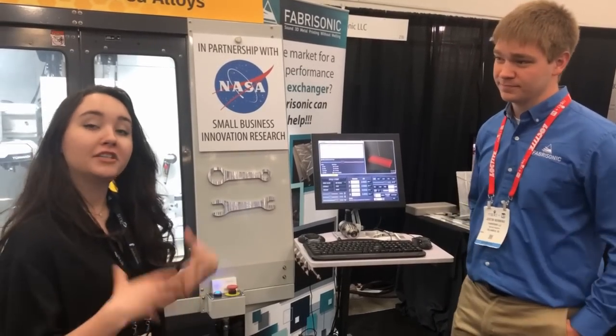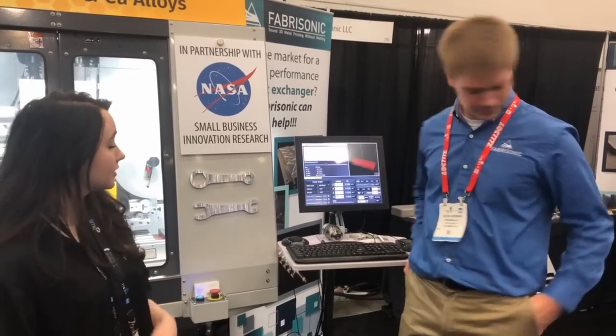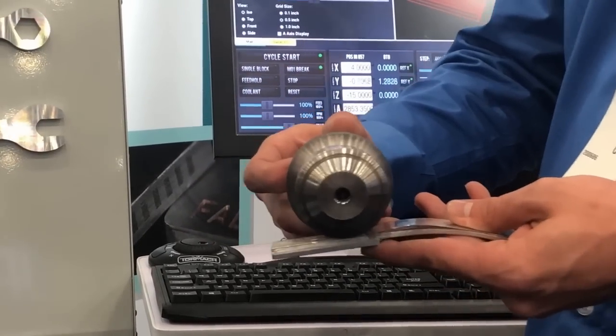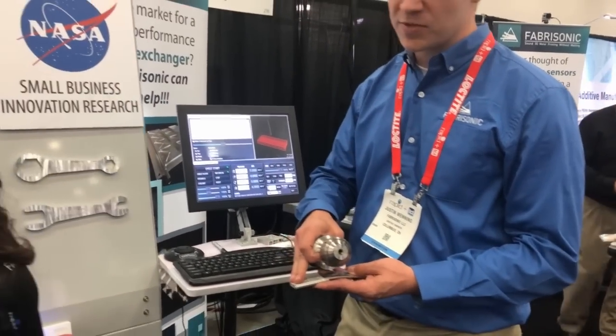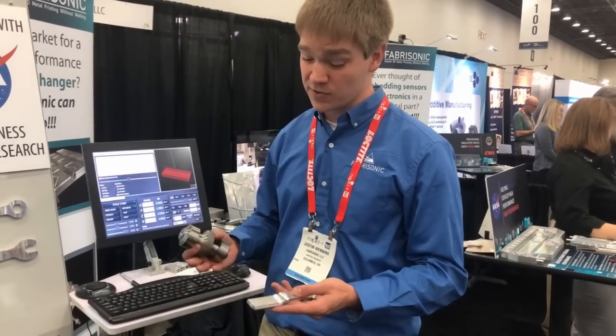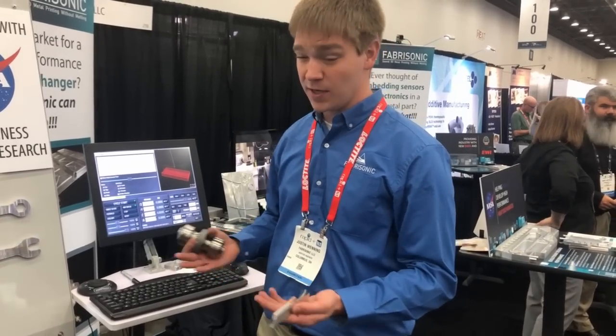At Fabrisonic, we do metal printing but we don't use powders. Can you talk about the UAM process and how it works? Instead of using powder, wire, laser, or any melting process, we use thin metal foils and roll our ultrasonic welding device across the top. As it rolls, we apply a downforce and oscillate the tool back and forth 30,000 times a second, scrubbing and ultrasonically bonding the materials to the substrate. By laying them side by side in a bricklaying pattern, we create net-shaped parts, then use CNC milling to add internal geometry or external features and deliver final parts.